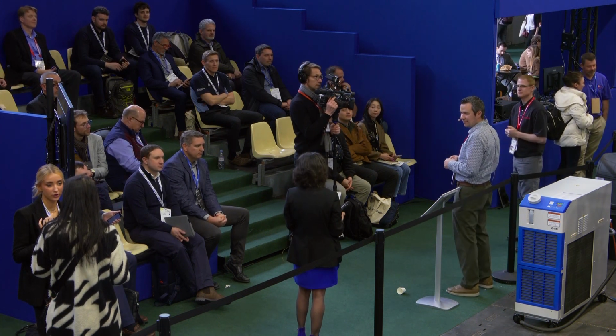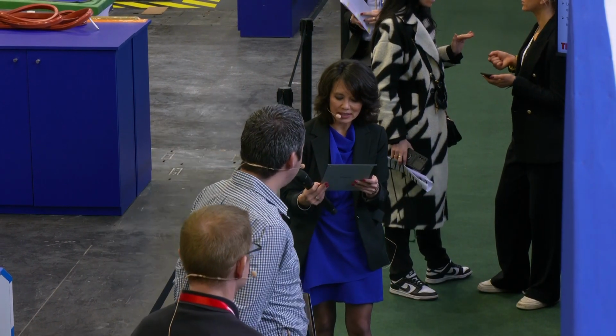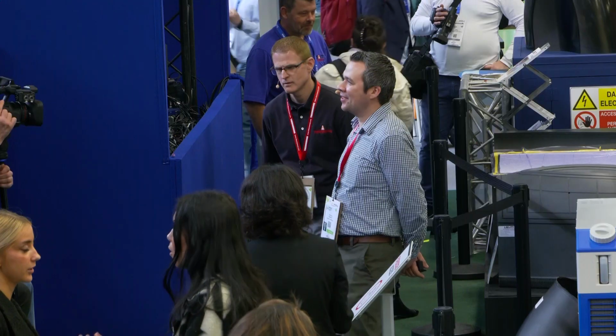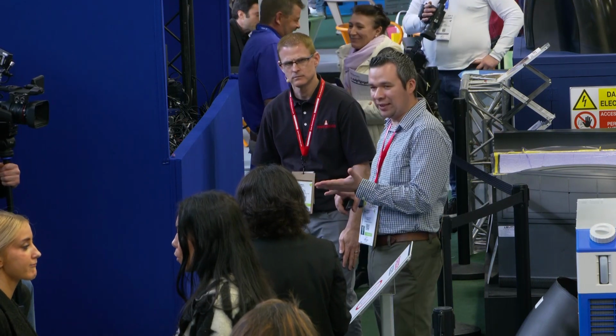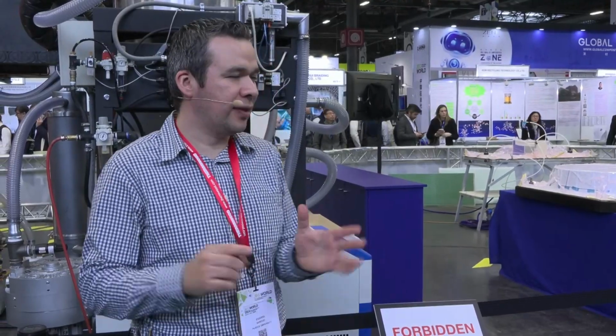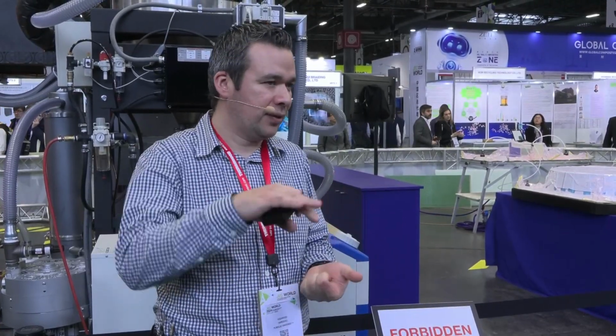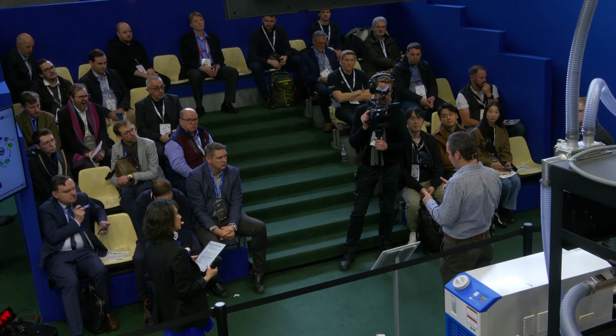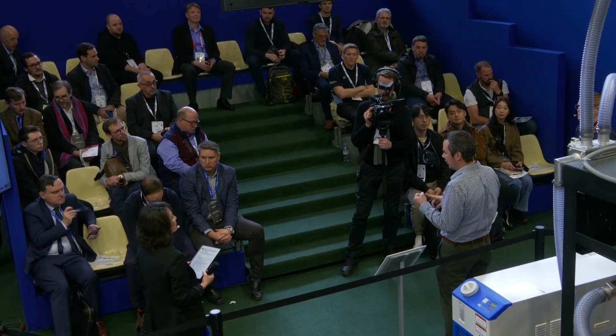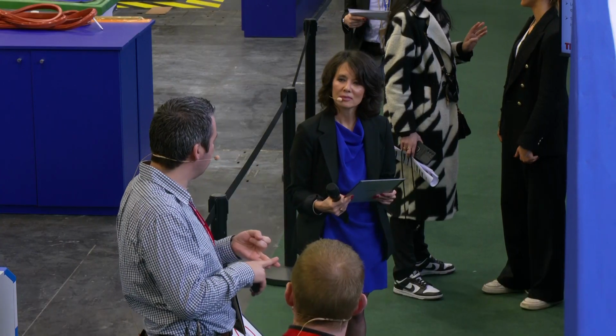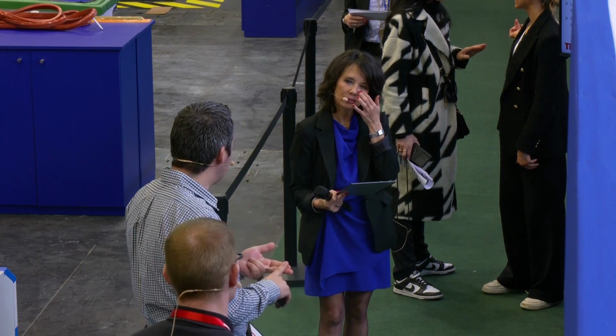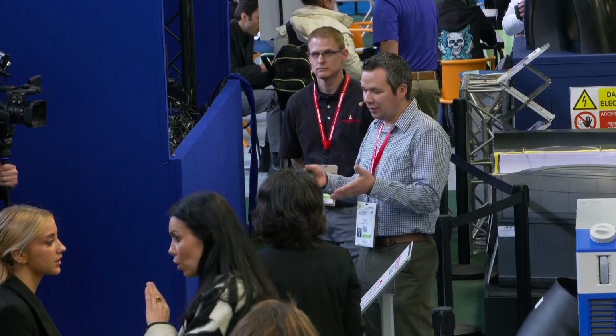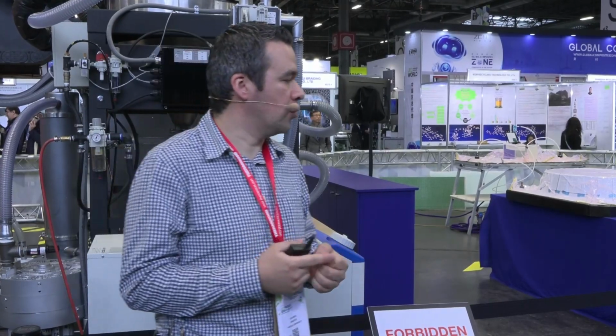Okay. And one last question for Eduardo. What physics are captured in Additive 3D? Yeah, there is a wide range of physics, including anisotropic heat transfer. There is local convection and radiation that depends on the features of the part. We even capture the heat that is removed with the compactor, either in the form of a roller or a tamper. We capture anisotropic viscoelasticity. We capture shrinkage, anisotropic shrinkage, not only due to the CTE of the material, but also due to the polymer crystallization that occurs in semi-crystalline polymers. We capture polymer crystallization and melting kinetics, so we can predict how the crystallinity is going to evolve throughout the entire print process. And we capture interlayer bonding driven by diffusion.